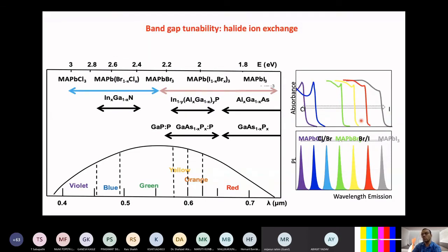What happens actually? As you go from iodine to bromine to chlorine, the dielectric constant of the perovskite semiconductor goes down. And once the dielectric constant goes down, then your electron-hole bound excitonic pair. What is an exciton? Basically a bound electron-hole pair. It's like a hydrogen atom, but instead of having the nucleus or the proton, you have the hole. Hole and electron bound together form an exciton. It's an electrically neutral species, and they are bound together because, as we have been taught in our 9th, 10th standard textbook, positive and negative charges like to stay with each other. And the binding energy between them is K Q1 Q2 divided by R, and K is 1 by 4 pi epsilon naught. Epsilon is the dielectric constant.